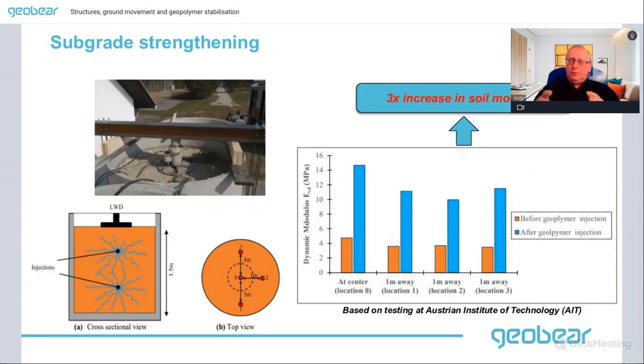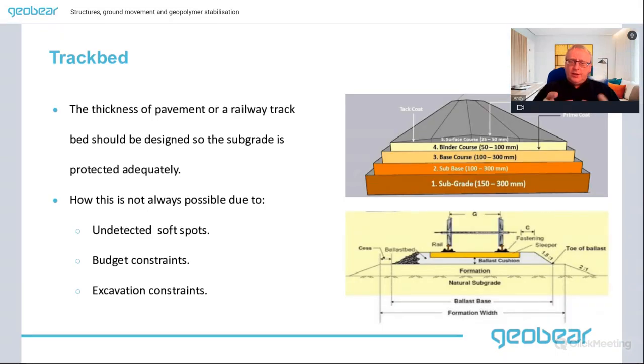Now there's something here about subgrade strengthening, and this is to look at the subgrade underneath your track bed if you've got a railway, or underneath your road. And there's lots of testing been done that shows that you can essentially treble the soil modulus by injecting polymer. And here's some testing done by the Austrian Institute of Technology, who were using falling weight deflectometer results to see how the dynamic modulus improves after polymer injection. And here's a test in a larger sort of concrete test cell. So this is really looking at railway applications.